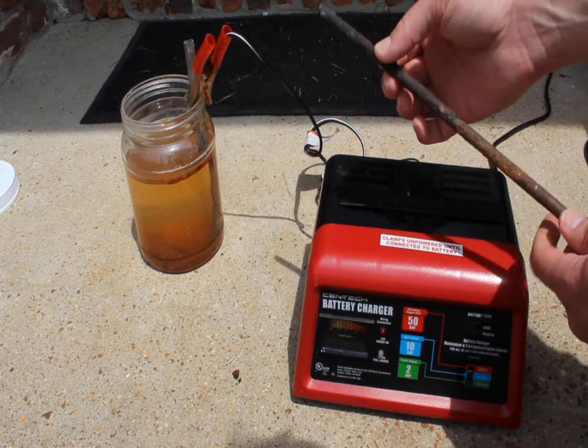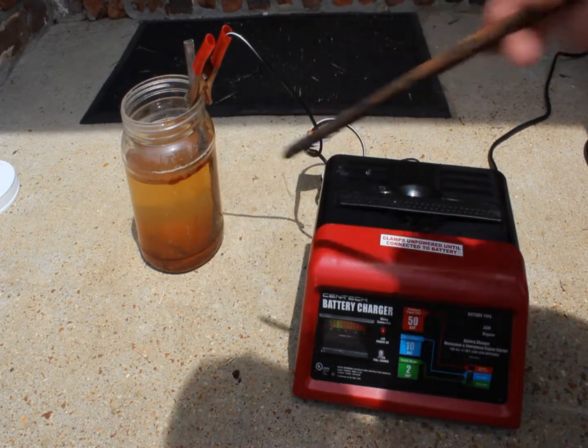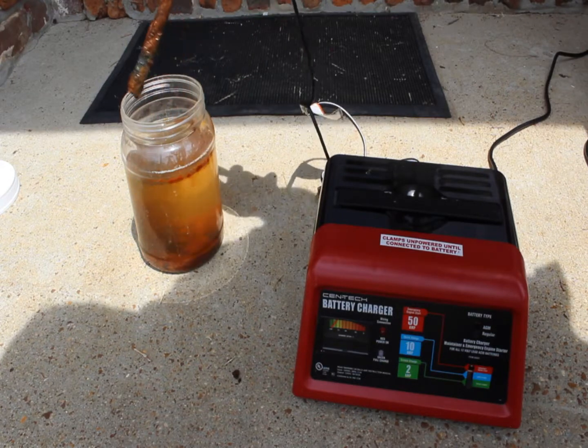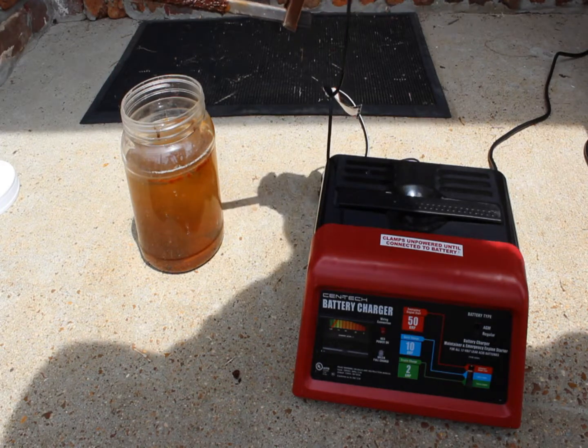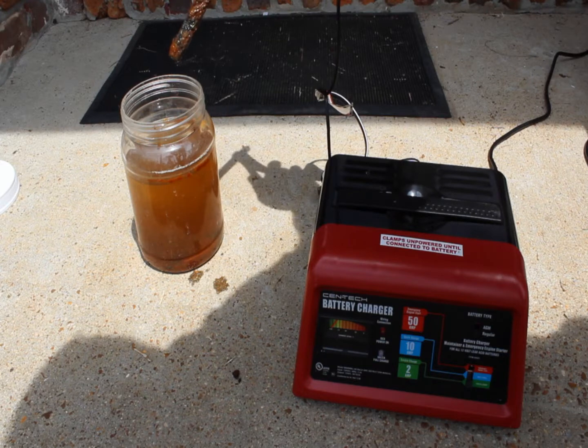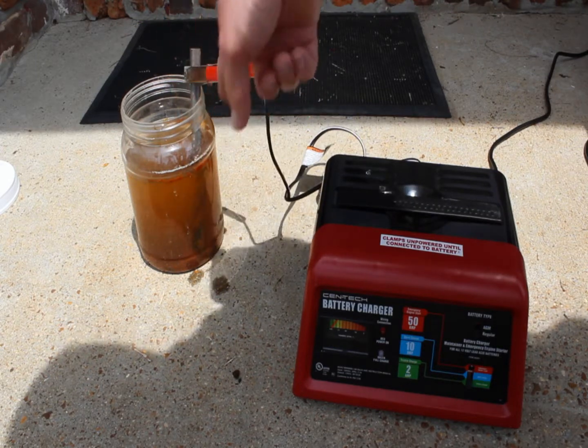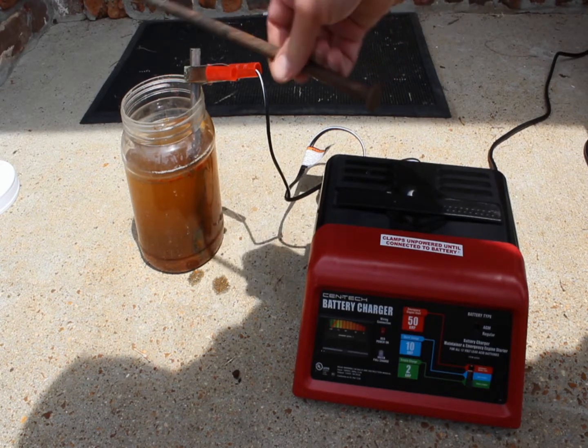It took about 24 hours. See how nasty our electrolysis bath is — it's all nice and gunky. Let's see how much our sacrificial anode took — it took quite a bit of rust. All that rust that's on the anode supposedly came off that nail, and that's quite a healthy amount. Also, you don't ever want to do stainless steel in this. Always hook the negative up to what you're trying to clean — positive goes on your sacrificial anode.